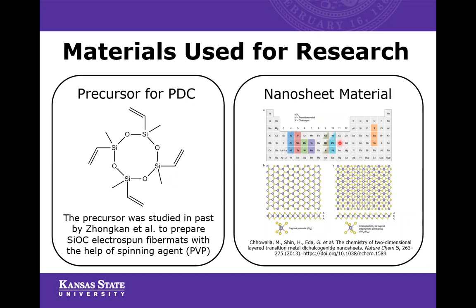Now, to talk about the nanosheet material or TMDs. TMDs are generalized by the formula MX2, where M stands for transition metal, which is highlighted here in the periodic table, and the two chalcogen atoms, which are highlighted here on the periodic table. So TMD is a nanosheet material which has a similar sheet-like structure to graphene. In addition, TMDs have an oxidation temperature higher than that of graphene, and moreover, the mechanical properties such as Young's modulus of monolayer TMD material is comparable to that of steel. As there are 40 different types of TMDs possible with the combination of transition metal and chalcogen, we get versatile chemistry. And among all of these TMDs, my study will concern molybdenum disulfide, which is one of the most studied TMD materials.